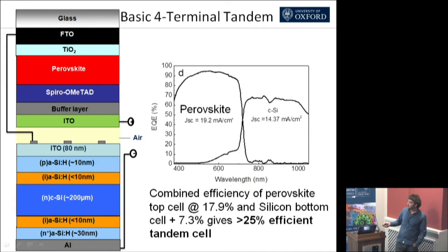And if we take a material that we tune to be precisely the right band gap to sit on top of silicon, there's some losses here in the silicon, and we stick a perovskite cell on top of a silicon cell, we can take, for instance, a 19-20% efficient silicon cell and bump that up to just a little bit over 25% already with the materials that we're using today. So the indication is this stuff could genuinely deliver 30% efficient wafers over the next few years, and then that could be translated into over 25% efficient modules, which you should compare to the most modules today are between 15 to 17%. So it can be a big step forward.